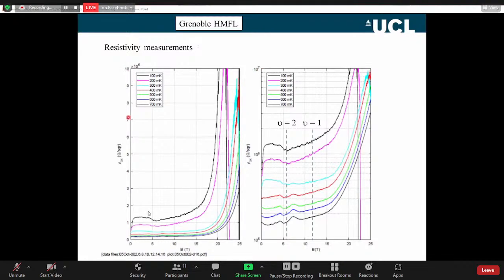If we plot the resistivity on a log scale, you can see the underlying Shubnikov-de Haas effect. At low fields the device resistivity is increasing. You can see the carrier density is not changing, so the periodicity of the Shubnikov-de Haas effect is not changing. This is filling factor 1 here. Although we're up to of the order of 10^6 ohms per square, we're still not losing carriers. We have as many carriers as we started with. So this localization effect is not losing carriers.